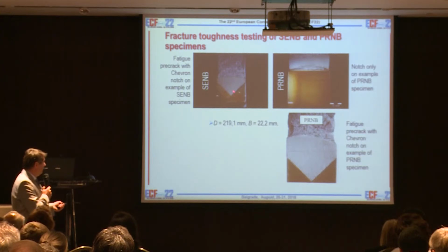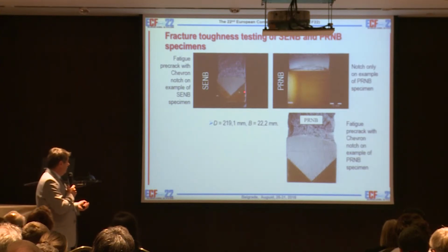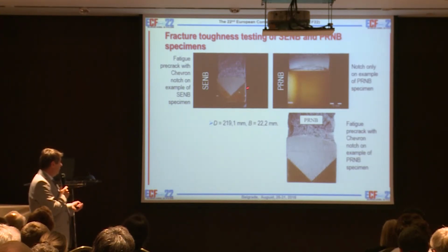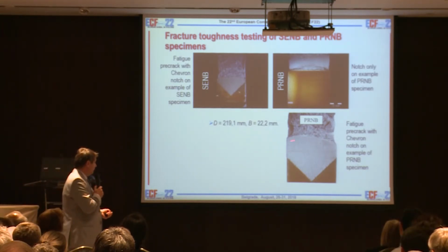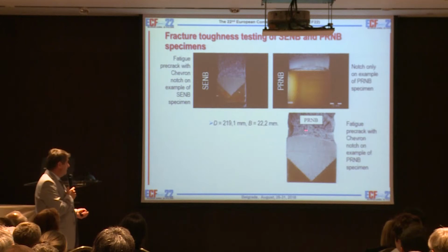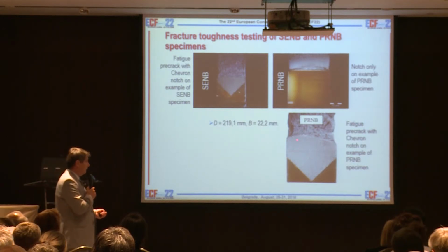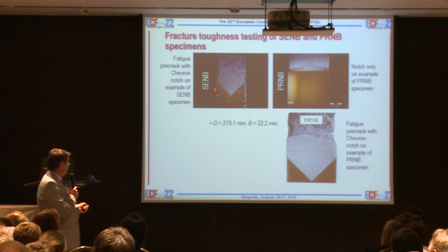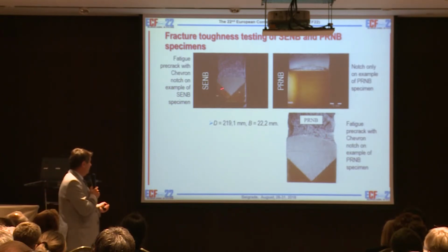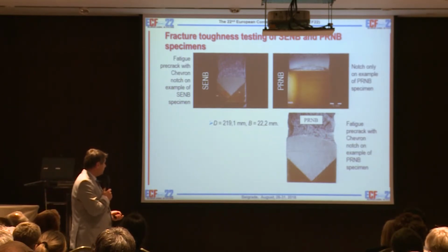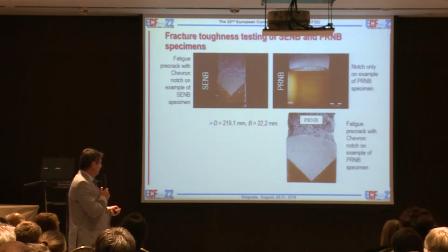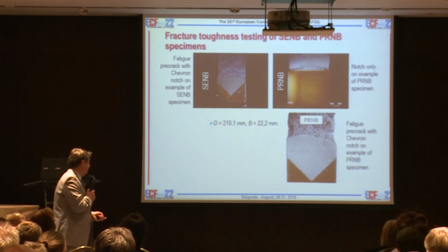In the 3-point bend specimen we made the Chevron notch, and also in the pipe rings, and then did the fatigue pre-crack front. You can see that the crack inside goes faster during fatigue pre-cracking than on the outside. And here you have a quite homogeneous crack front. So this is the data about the diameter and the thickness of the pipe. This is the outside diameter.